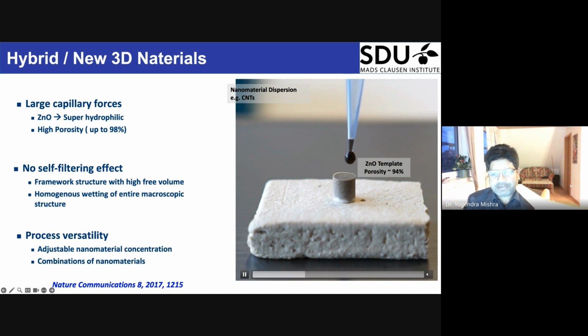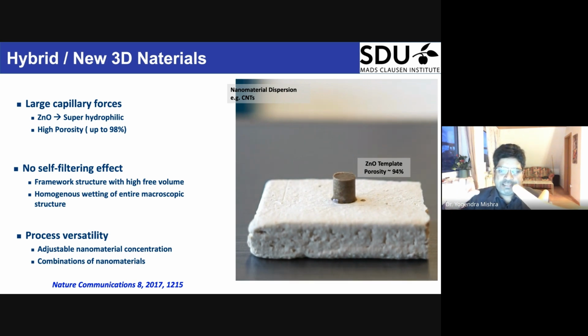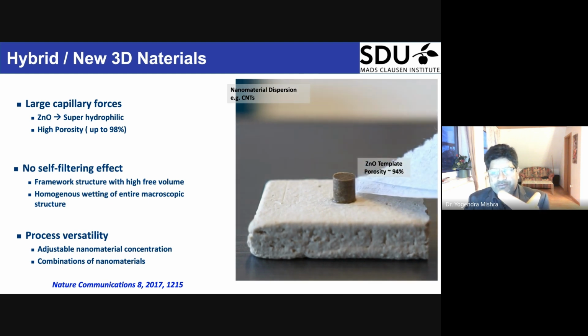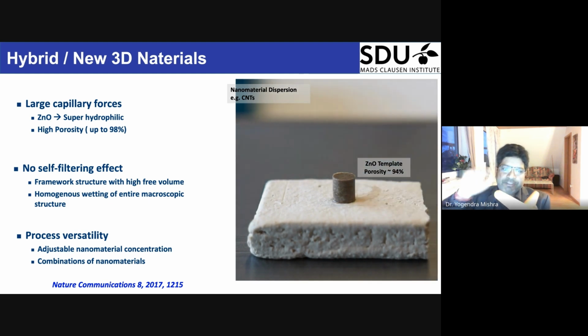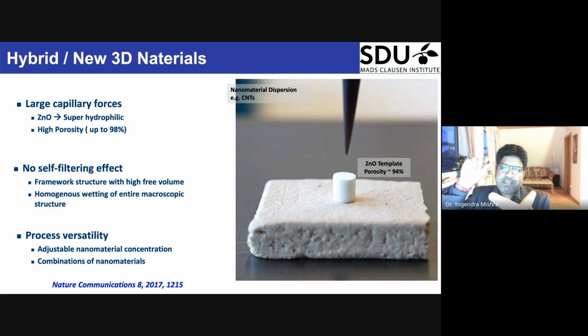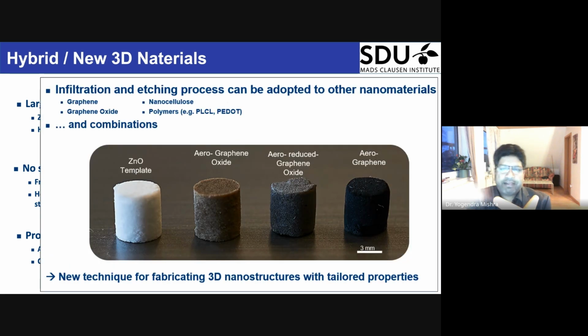This is the carbon nanotube solution which was dropped on these tetrapods. You can see that the CNTs are wetting the entire network very uniformly. Now it is a composite material. Whatever you wish to add on top of this tetrapod network, you can add. And that means you now have two functionalities in the composite form, zinc oxide and carbon nanotubes. If one requires a composite, one can use it as a composite.